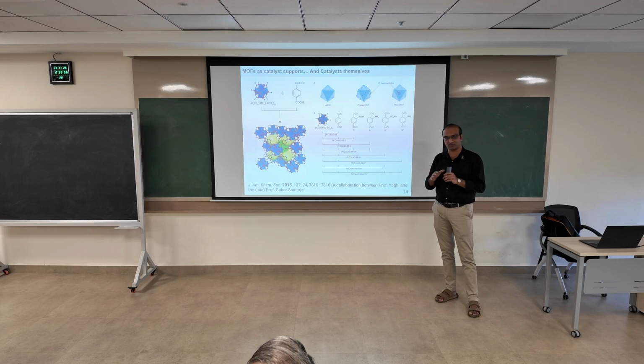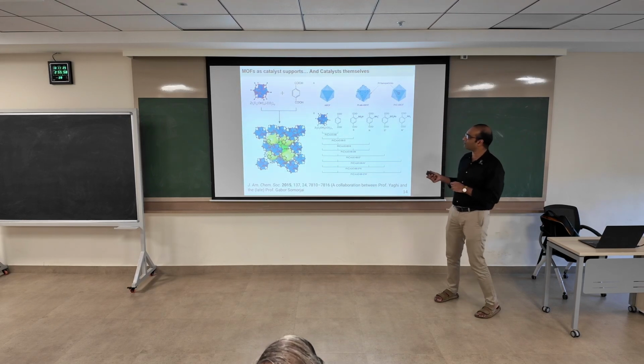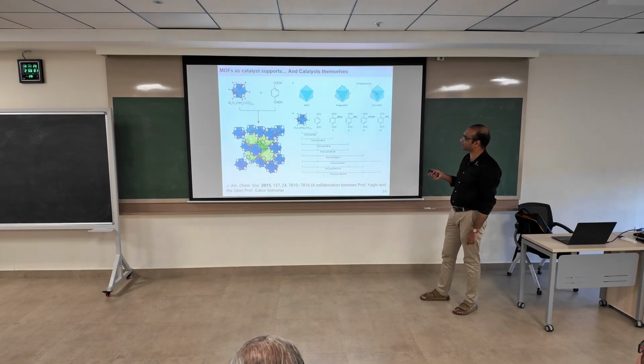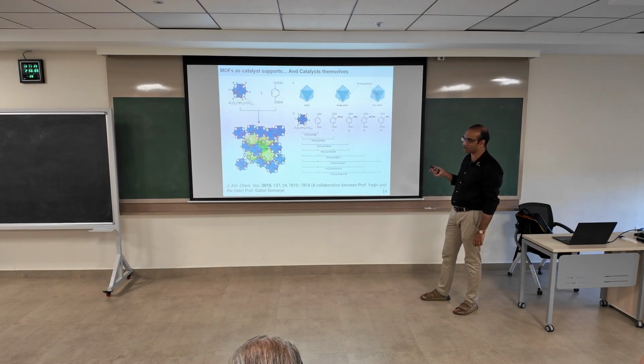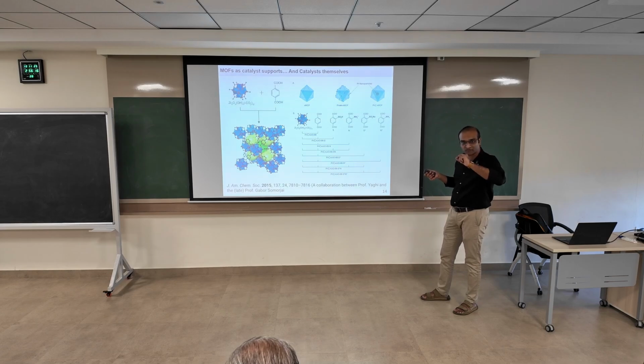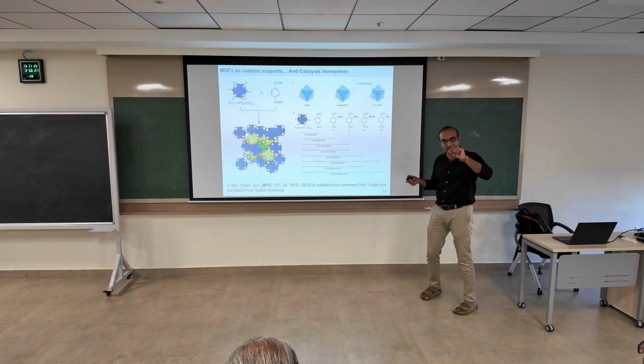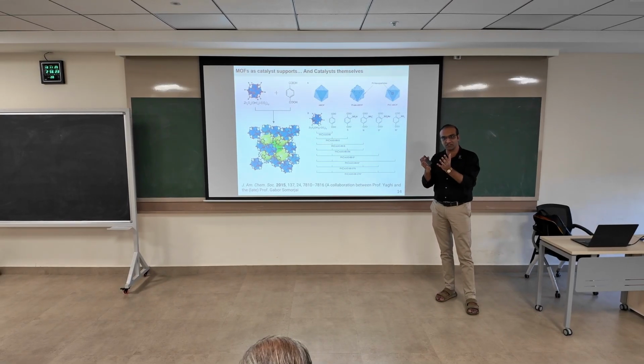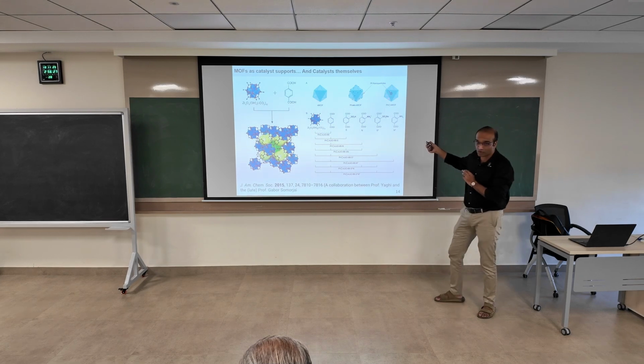So this particular MOF, what you could do is you could change the acidity of these linkages, right? You can put certain functional groups and you can change the acidity based on whether it has a proton or not, and then use them to do cracking, okay? And they tried with MOF where you can load the platinum inside the MOF within the pores. If you have the right linkage, for example, if you have NH3, it will coordinate to a platinum atom, and if there are enough NH3 linkages, you can control the amount of platinum that is there. And you can exclusively put it inside the MOF.